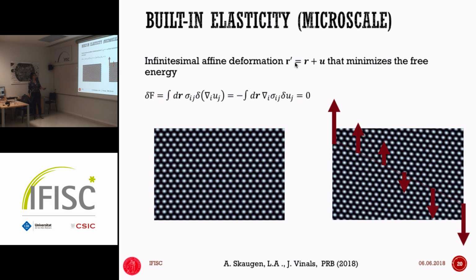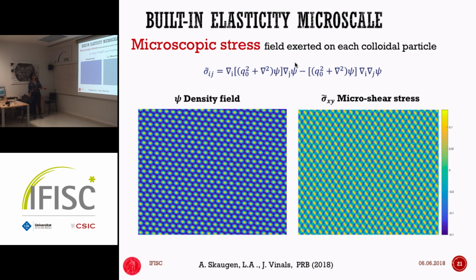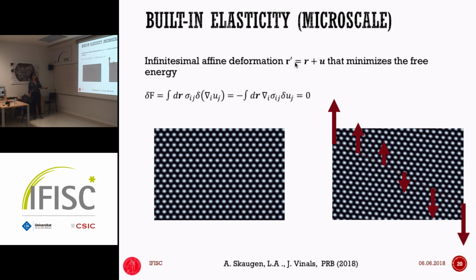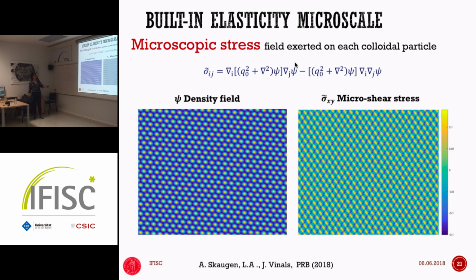Okay, so if we do now a variation of this free energy with respect to variational changes in this deformation field, we can derive this expression that looks very much like the linear elasticity. So that leads us to the definition of a microscopic stress field. There's a little bit of variational calculus involved in it, nothing complicated, but kind of technical. But the point is that you can carry out those partial derivatives, and you can calculate a microscopic stress field from the form of the free energy. So if you have a different free energy, that's different. This term here comes exactly from the gradient expansion. If I had another non-local term, it would come up differently. But for this particular form of the free energy that we are using, we can derive a microscopic stress.